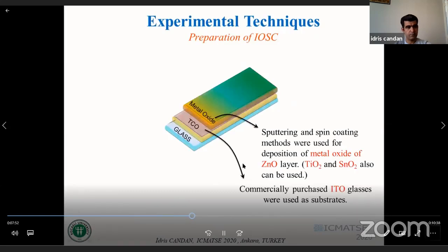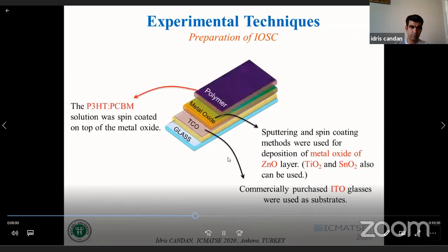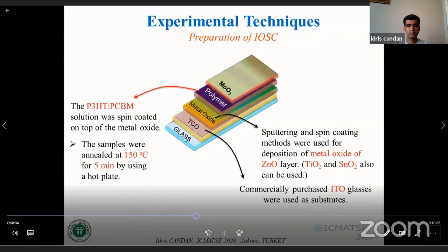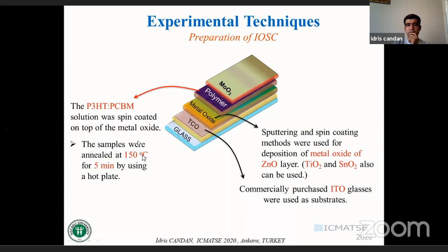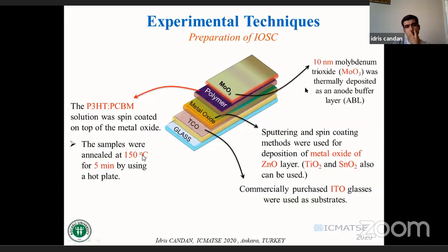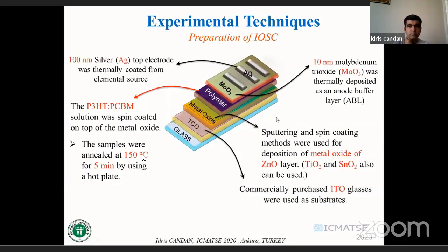Now I would like to give some information about our solar cell device structure. As you see here, we used a glass substrate, TCO coated glass substrate. We coat a metal oxide, zinc oxide. Also titanium dioxide or tin oxide can be used in this layer. The polymer photoactive layer P3HT:PCBM is spin coated on top of the metal oxide, and then molybdenum trioxide, around 10 nanometers, is thermally deposited on top of the photoactive layer as a buffer layer, and a 100 nanometer silver top electrode was thermally coated from an elemental source on top of the molybdenum trioxide.